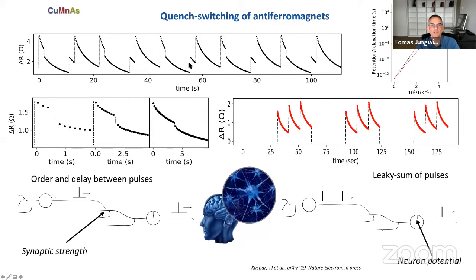So what we get from this is that the signal we can write in these devices depends not only on the amplitude of the pulse, but also on the order of pulses. If we first deliver the stronger pulse and then the weaker pulse, we have this falling edge, but in the reverse order, we have this rising edge. And we can also measure the delay between pulses, because the falling edge, what you see here, depends on the relative delay between the first and second pulse.